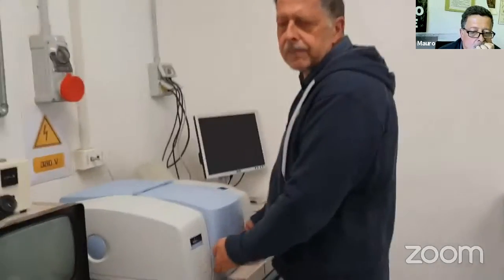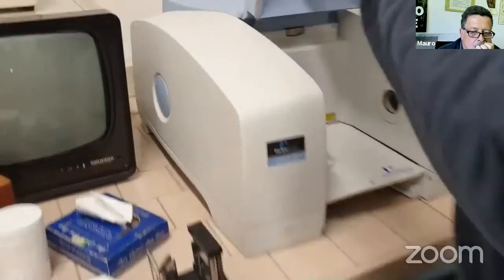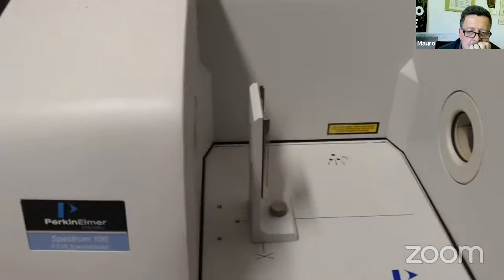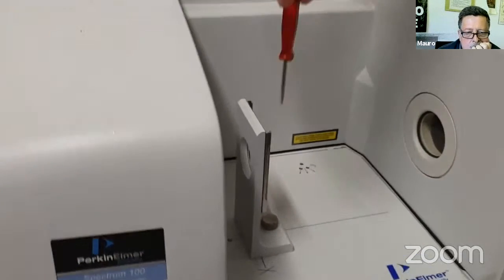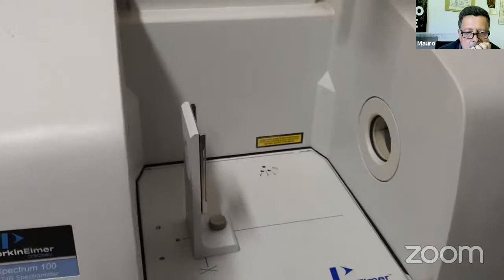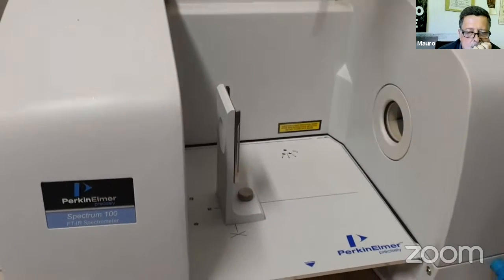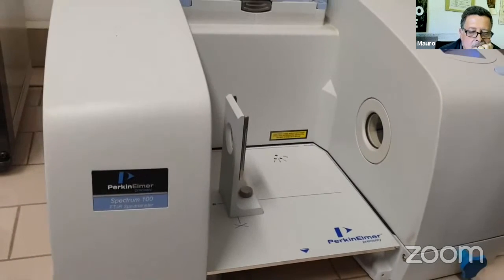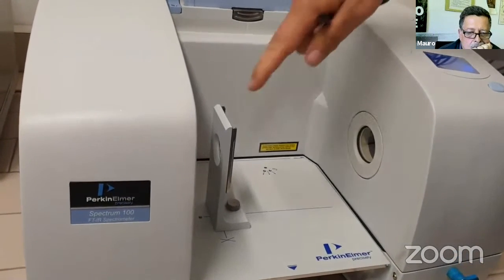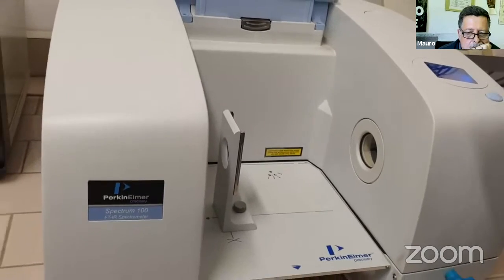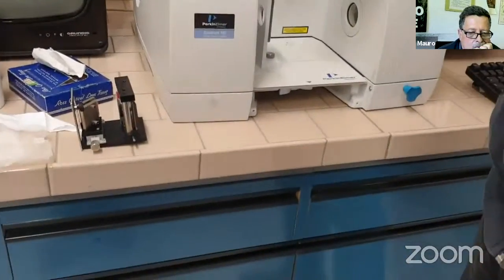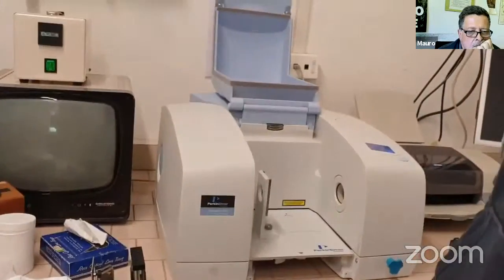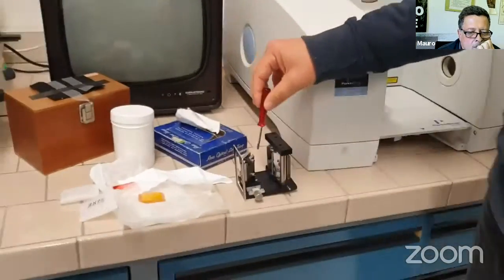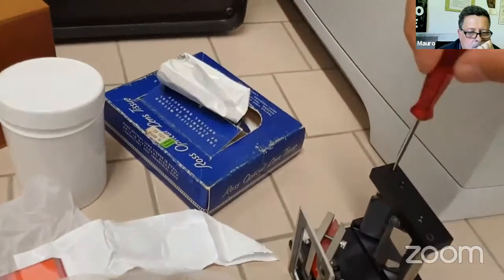This instrument can work in two configurations, namely transmittance of samples in pellets. So samples are reduced in pellets and they are inserted in an infrared beam path so that the detector reveals the absorption band due to the infrared vibrations of the sample. The other way to use the infrared spectrophotometer is by attenuated total reflectance.